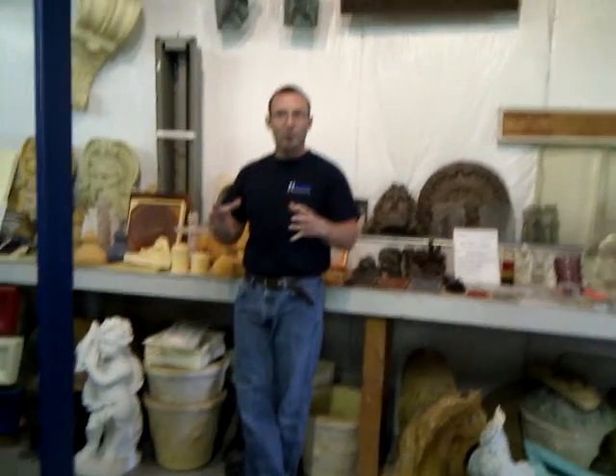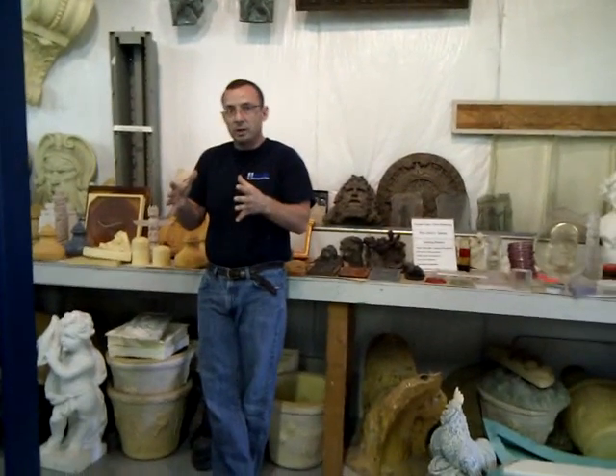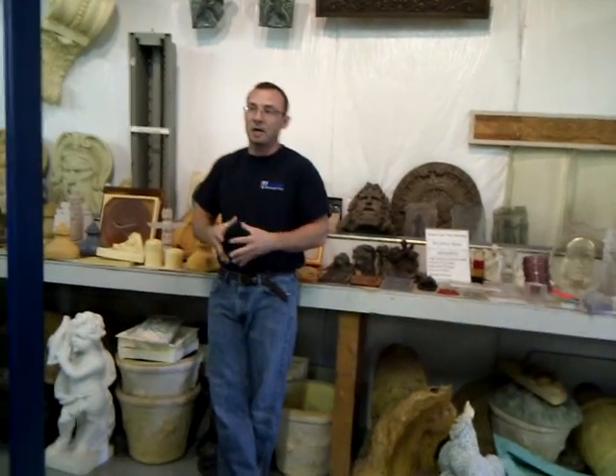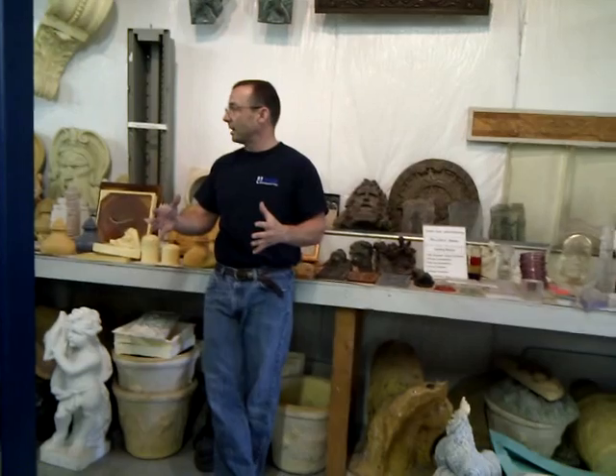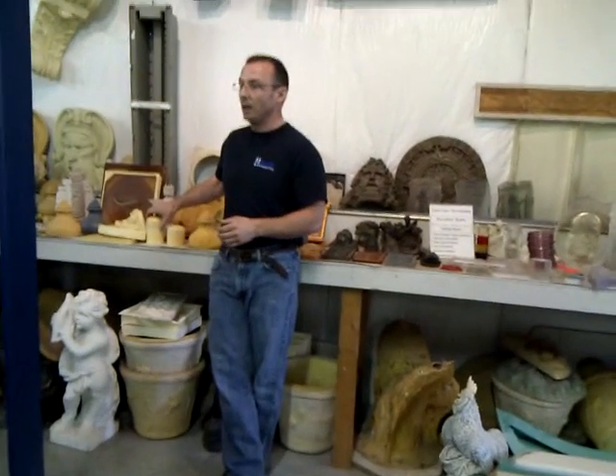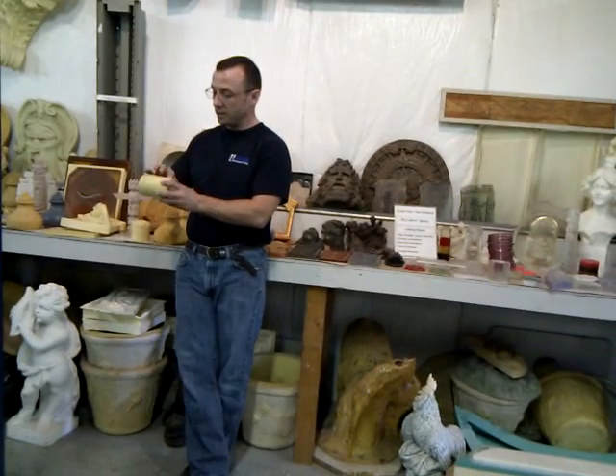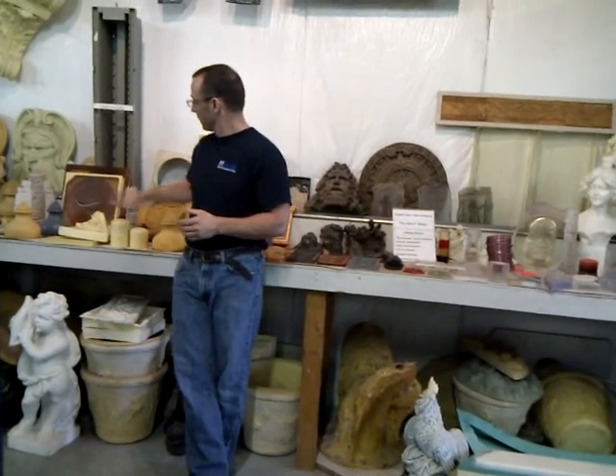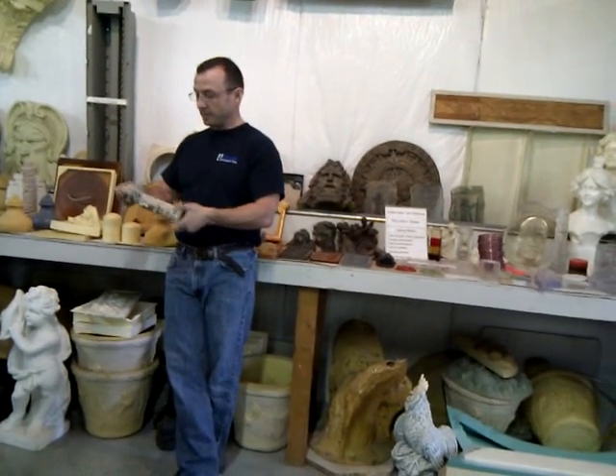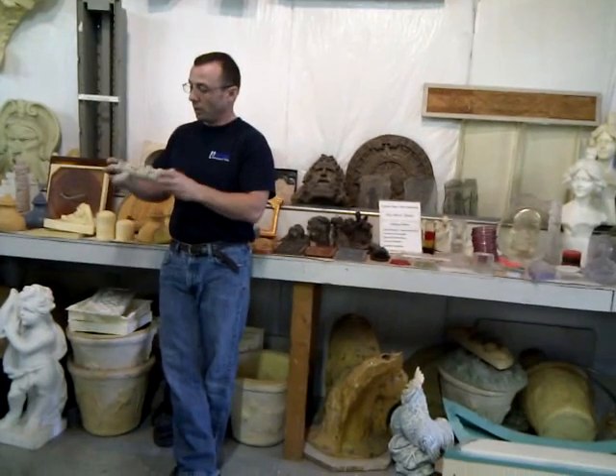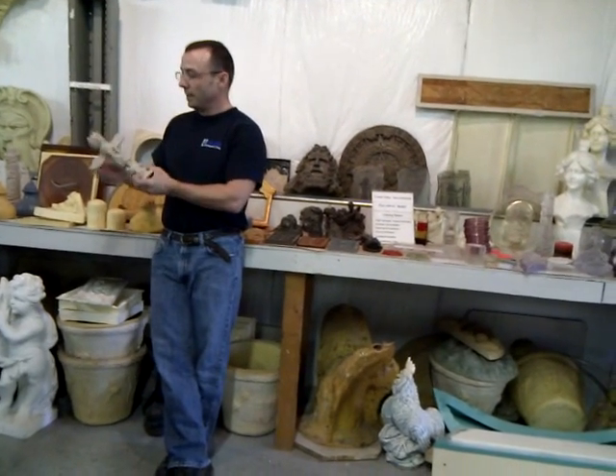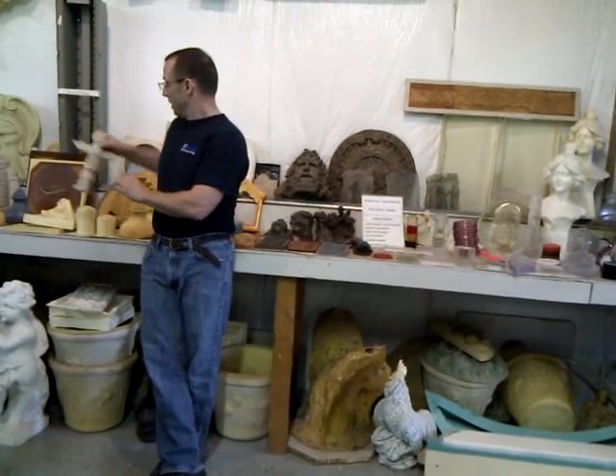Now there's a lot more foam in there. It wants to get bigger, but the mold holds it in shape, and so we end up with a part that is cast at 12-pound or 14-pound density that has a little bit of a resin skin on it. And that's required to get a good part. These are just free rises. You can see that the surface quality is not great. This one is packed or cast in a closed mold, and the surface is very good.